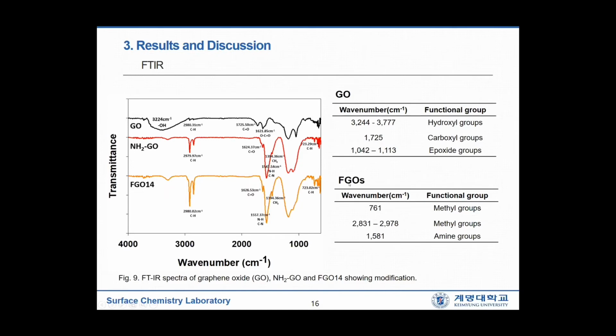In the FGO sample, methyl groups appear at 761 wave number and 2831 to 2978 wave numbers, and the characteristic peak of the amine group appears at 1581 wave number. Since the peak intensities of hydroxyl, carboxyl, and epoxide groups in GO are decreased, and the peak intensity of the amine group in FGOs is increased, we can assume that the amine group is successfully introduced to the GO sheets.